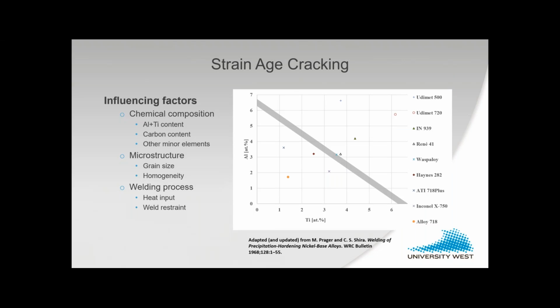So there are various influencing factors regarding strainage cracking, and as I said, it's primarily something for the precipitation hardening alloys, but specifically for the gamma prime hardening alloys. So aluminium and titanium are the two key elements regarding the gamma prime phase formation. So the more aluminium and titanium you have, the more gamma prime you have, and the higher the risk of strainage cracking. Then carbon content has also been shown to have a high importance. Carbon is a carbide former, of course, and the carbide formation at the grain boundaries can sometimes prevent grain boundary sliding, which can be beneficial towards strainage cracking, as well as for ductility dip cracking. Then there are other minor elements like sulfur, boron, phosphor, which also have some effect.